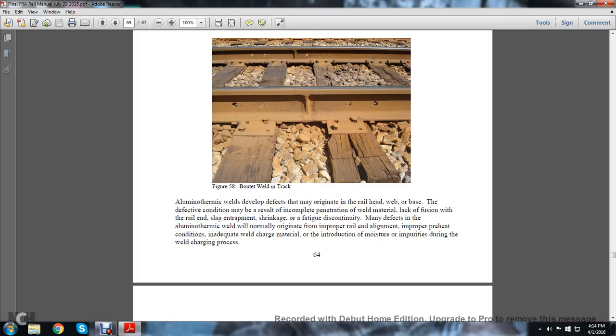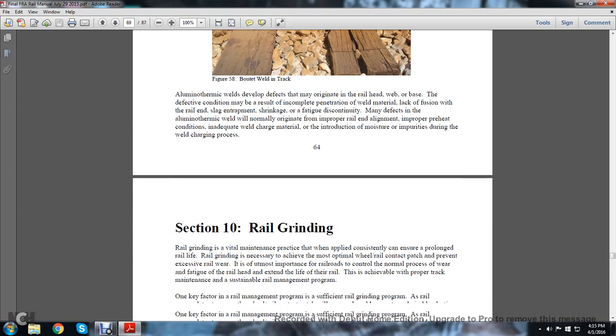Aluminothermic welding defects originate in the railhead, web, and base. The defective conditions may result from incomplete penetration of weld material, lack of fusion, rail end, slag entrapment, shrinkage, fatigue discontinuity. Many of the defects of aluminothermic welding will normally originate with improper rail alignment, improper preheat conditions, and inadequate welding charge material introduction, moisture, and impurities during the welding charging process.